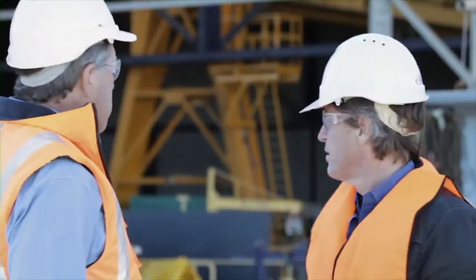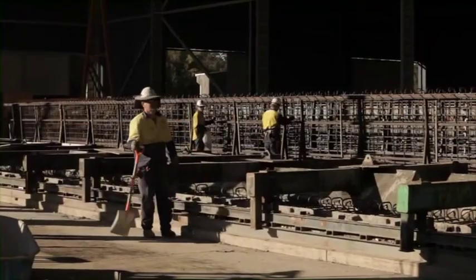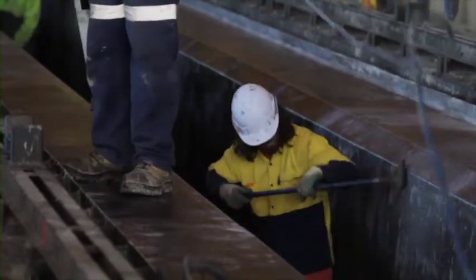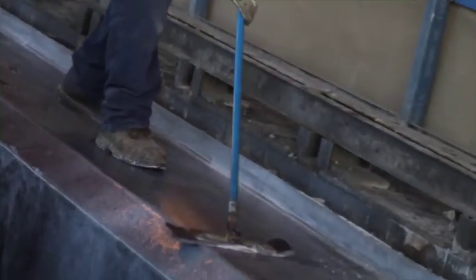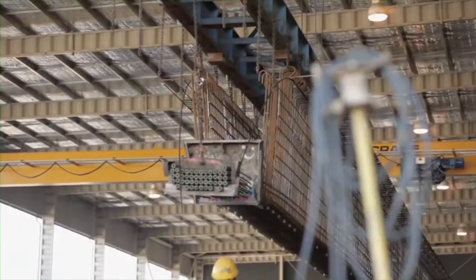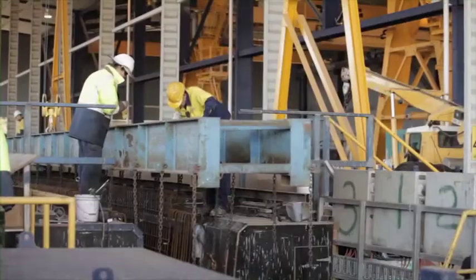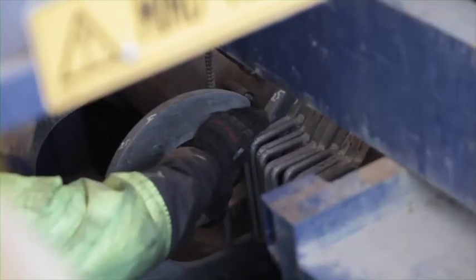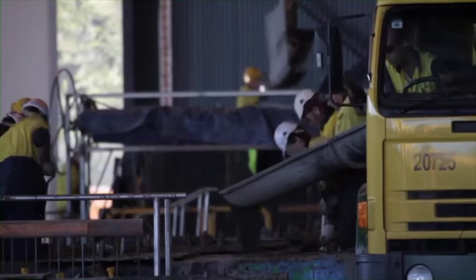So every day you'll see 5 beams which will come out of the mould. We'll then do the setup process. We've got prefabricated reinforcement cages which are already assembled. The mould gets cleaned, it gets oiled up and prepared, any gaps sealed, and then the reinforcement cage will get lifted in one piece. We then connect the reinforcement strands which are already pre-assembled in the bottom of the cages. They're coupled up. We then stress those strands, complete the installation of other bits and pieces into the mould. The strand is then stressed to full stress. We then complete the final checks and processes, and then concrete is placed, and at the end of the day